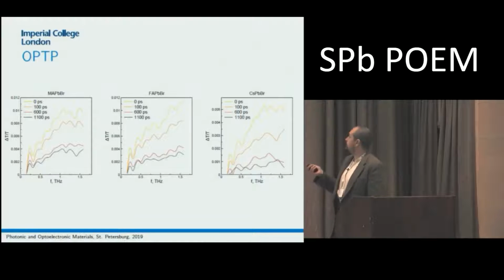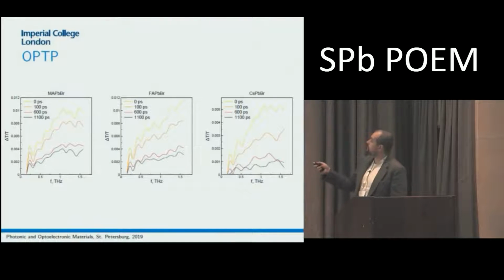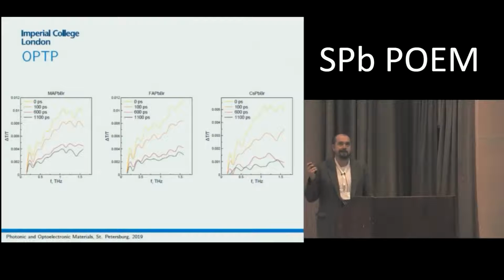And the rate of change is slightly different. Cesium reveals a much lower change of signal, less than 1%, while for MAPI and FA bromides we have a change of signal of about 1%. Again, the pump is about 36 microjoule per centimeter squared.